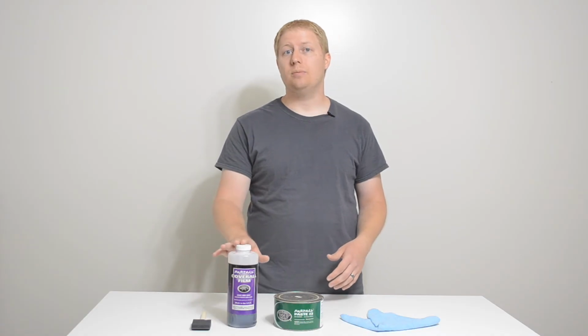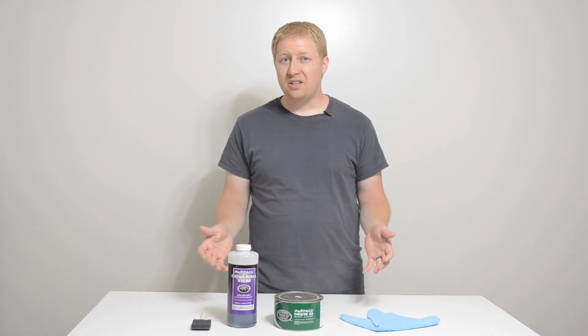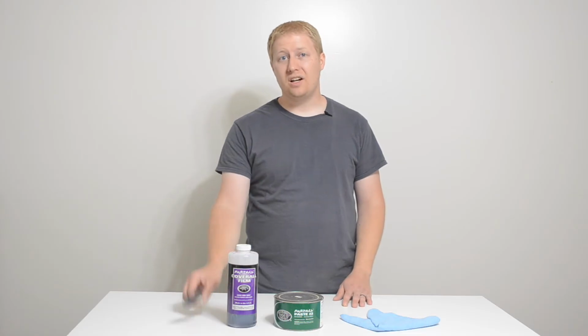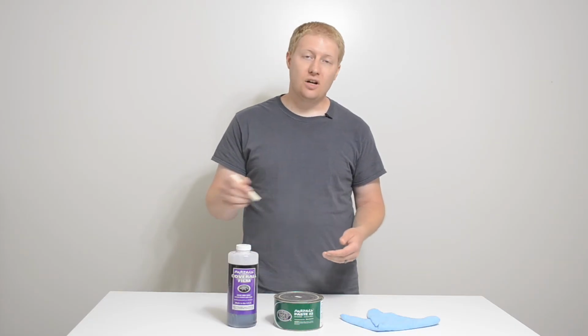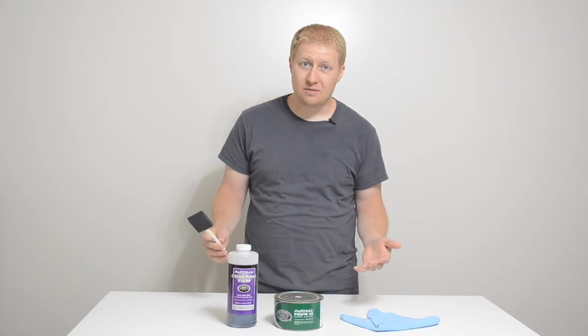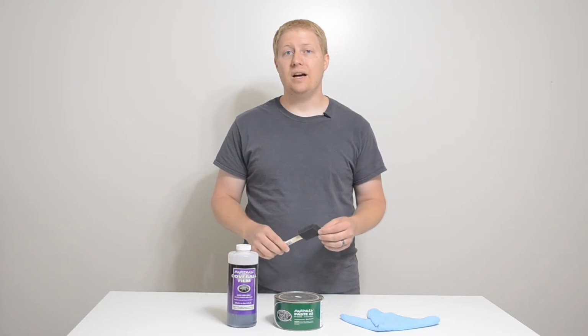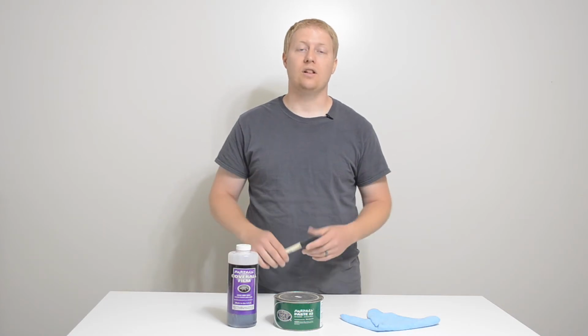Some people say that in order to avoid streaks, you really need to spray your PVA into the mold. Maybe it's just because I use smaller molds, but I've had really good luck with just using a brush. I've tried brushing PVA on with a regular horsehair brush or something similar. It leaves streaks, but I found that if you use a foam brush, it works extraordinarily well. I don't get streaks. When you brush it on, sometimes you'll get some little bubbles around the edges in some places, but my experience has been that those bubbles pop as it dries and you get a really smooth glossy surface, as long as your mold also has a glossy surface.